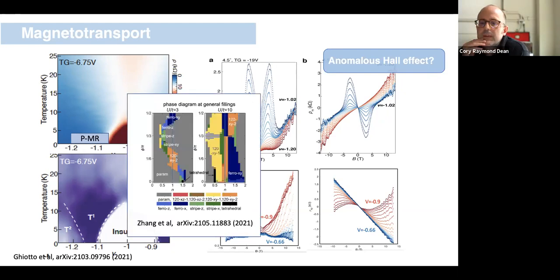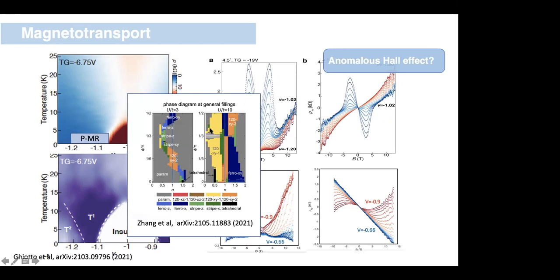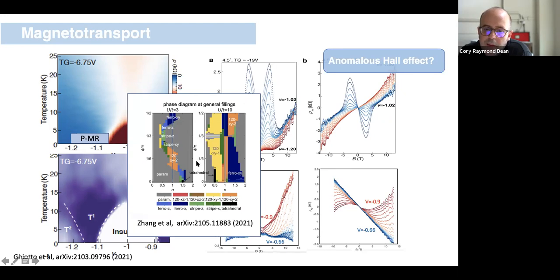One of the things we've done is to discuss this with our friends at mostly the Flatiron. They came out with a paper recently, on the arXiv, in which they tried to calculate, for a system like ours, what you might expect the ground state ordering to be around this metal insulator transition, and how that evolves as a function of interaction parameters on the vertical scale and doping on the horizontal scale. All I want to point out is that, forgoing the details, they find it plausible that you might expect different magnetic ordering states on the overdoped side versus the underdoped side. And the precise nature of those states would depend on the precise interaction strengths in the system. Okay.